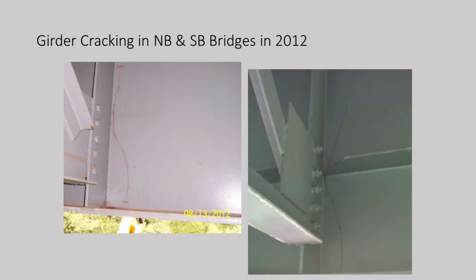If you take a look at the northbound or the southbound bridge, you can see the reason for the curvature. This is the crack that formed in that bridge, and the curvature is because the crack goes through this narrow gap detail here between the vertical and the horizontal stiffeners. If you look, the fillet welds that attach the vertical stiffener and the horizontal stiffener to the web are in close proximity to each other, and they probably touch.